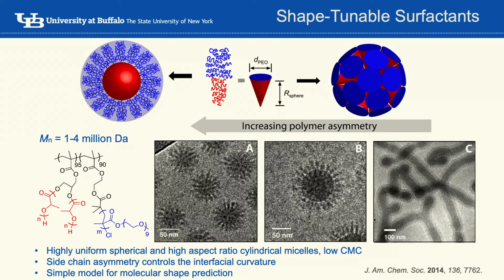This is molecular weight of the individual polymers. So we measure them by GPC light scattering. No, this is molecular weight of individual polymer, no aggregation. So each polymer is this big. So what we've done is we use gel permeation chromatography coupled to light scattering detector. We measure the size of each chain, and then we can also measure the size of the aggregate, and then we divide the two, and you can calculate the number of chains in the aggregate.